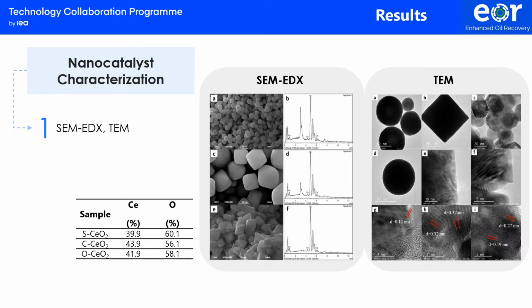High-resolution transmission electron microscopy reveals that the 111 crystal phase dominates the surface of the cubic nanoparticles, with an interplanar spacing of 0.32 nanometers. This is the thermodynamically most stable crystal facet. The orthorhombic particles are enclosed by the 200 and 220 planes, with interplanar spacings of 0.27 and 0.19 nanometers respectively.